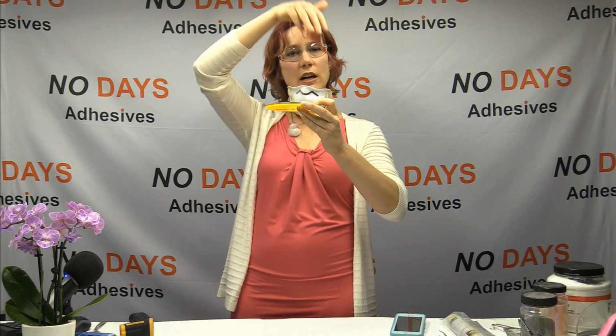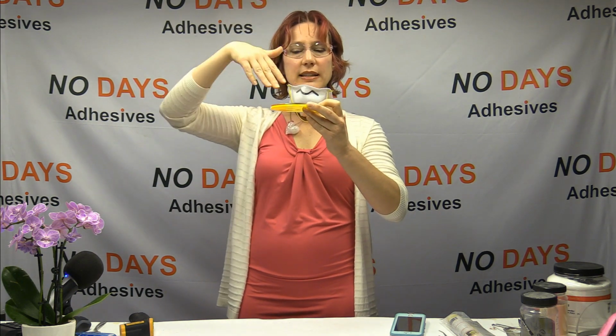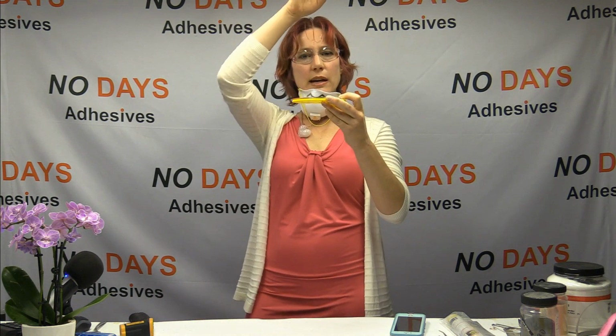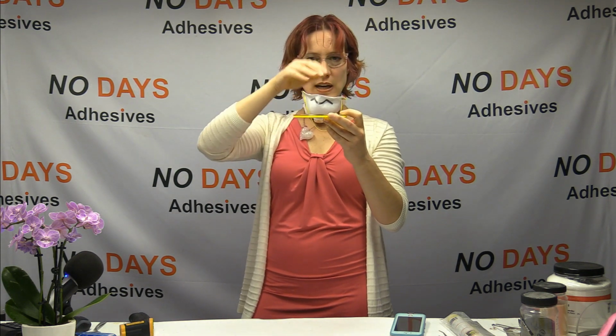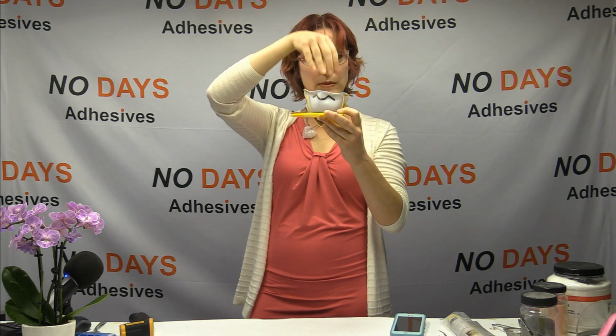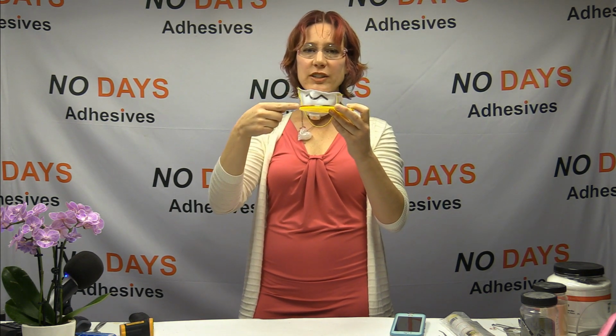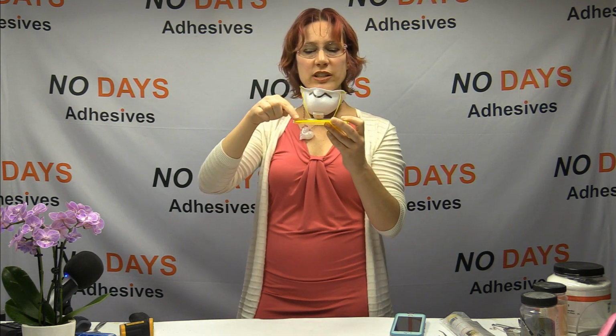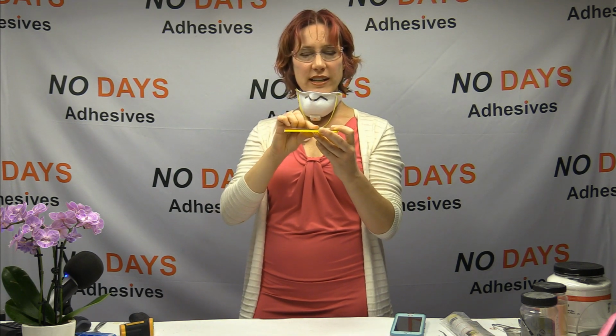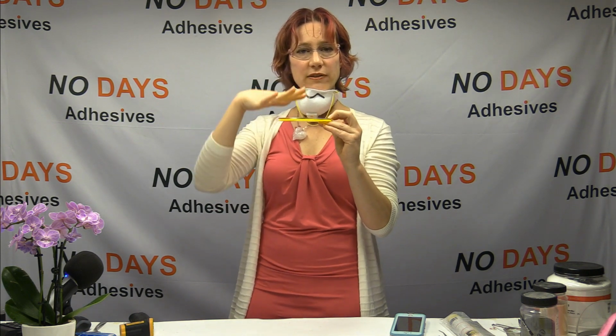here's our glass piece in the kiln. We've got our elements above, right? As the glass is getting warmed up, the heat is coming down across the glass. All of the glass is getting heated from above, but the sides are also getting heated. The sides are getting hotter because they're getting heated from above and also from the sides. So the edges of this are going to heat up, and they have a chance of sealing shut before the middle of the glass has relaxed and fallen. So there's a greater chance that we're going to catch little bubbles in between our designs.